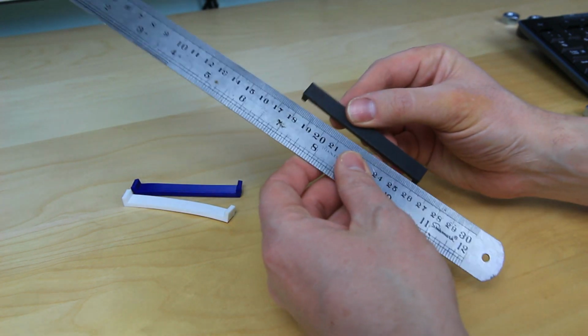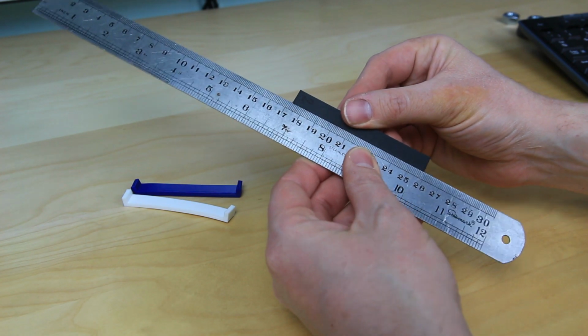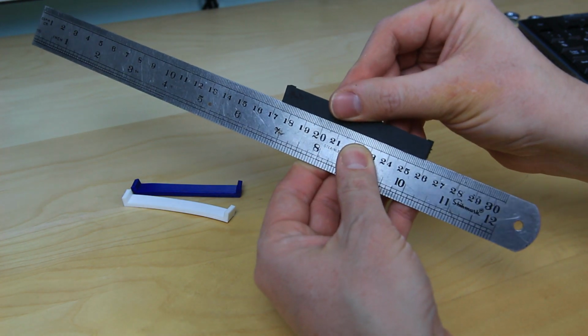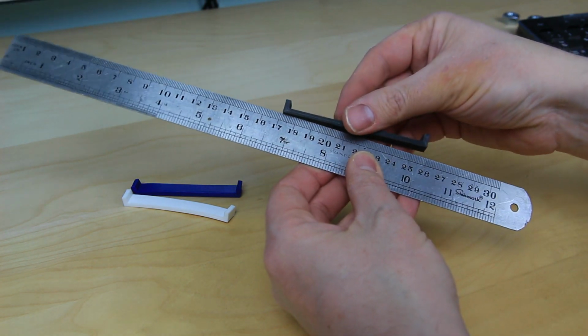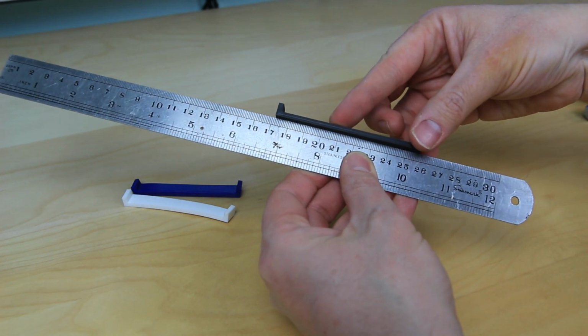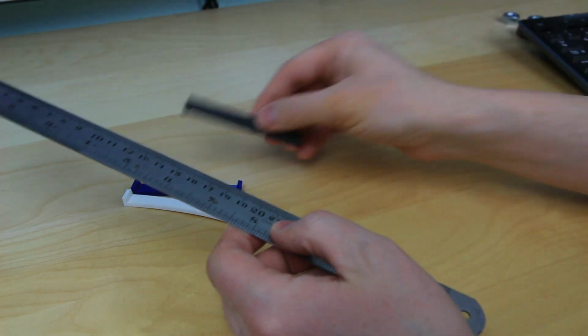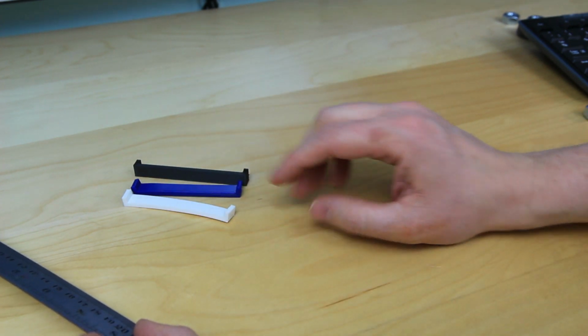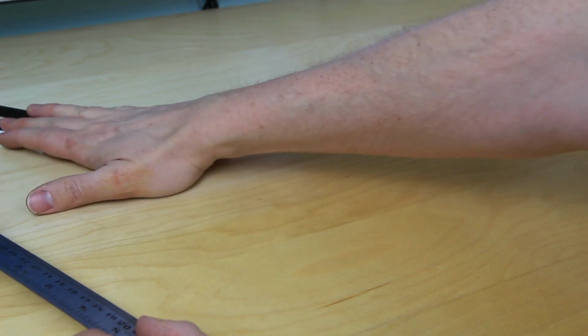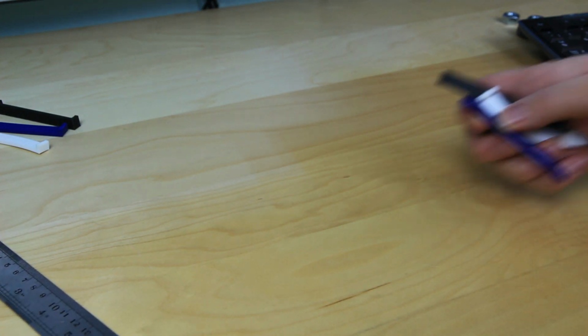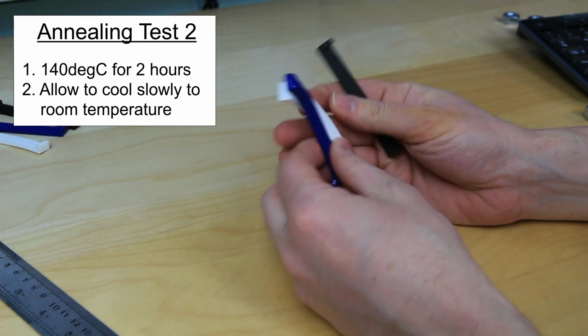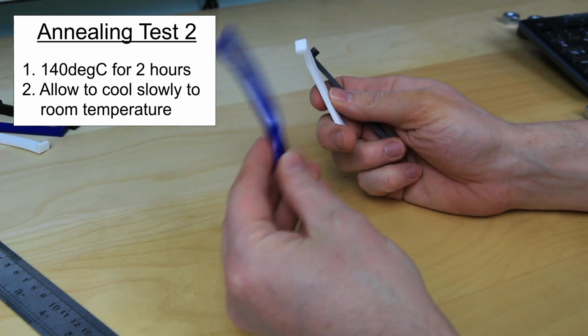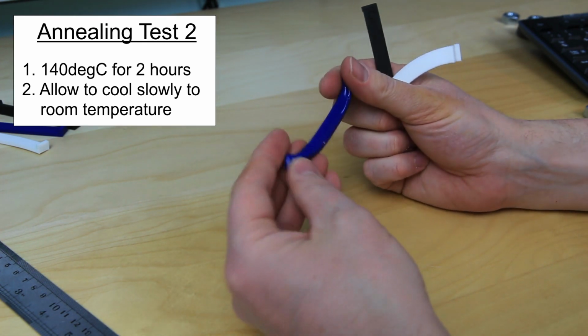But the nylon is absolutely spot on. I have looked at this quite closely and there is 0 deflection at all. So that's the 100 degrees, so already we're too hot for the PLA and the PETG, but we're not really here for them. Let's look at the 140 for 2 hours, the second annealing trial, and the blue PETG is